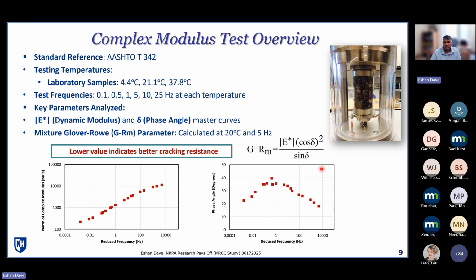So quick summary of test procedures itself. Complex modulus, we followed the AASHTO T342 test protocol where the testing was done at 3 different temperatures, and at each temperature we have 6 testing frequencies that allows you to really generate the master curves of your complex modulus or norm of complex modulus, which is dynamic modulus, and the phase angle. And that's important because we need to have that parameter in order to do different type of modeling where we can simulate the properties of asphalt mixture, its response at different frequencies and temperatures with different traffic speeds, with different climatic conditions, and so on.